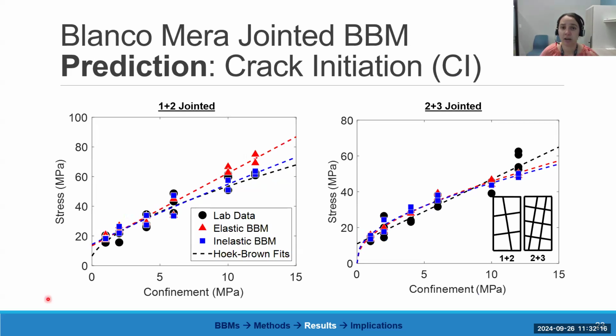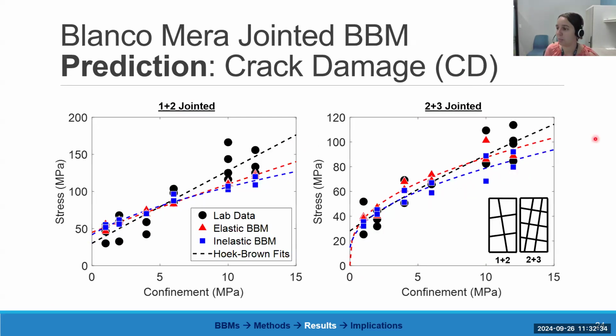So we also looked at crack initiation thresholds as well. You'll see that both the elastic and inelastic block BBMs were able to predict CI values for the 1+2 jointed case, and same thing for the 2+3 jointed case. Both model types were able to predict the values. I'm going to start to sound like a broken record, but this is also crack damage thresholds if you're interested. We see the same slight underestimation of crack damage thresholds for these two higher confinement cases in the 1+2 geometry, which makes sense since we saw a slight underprediction in the strength, and CD and strength are related. But also we didn't see that in the 2+3 jointed case where the predictions were quite good.